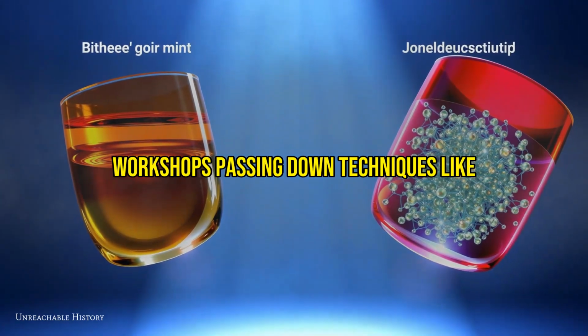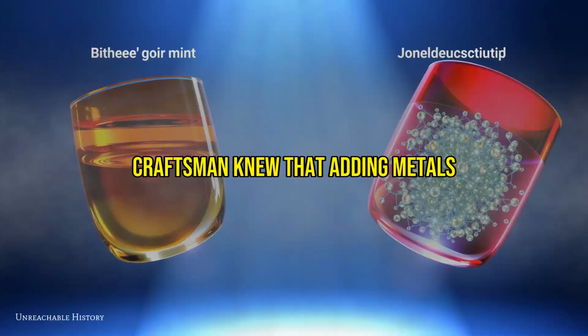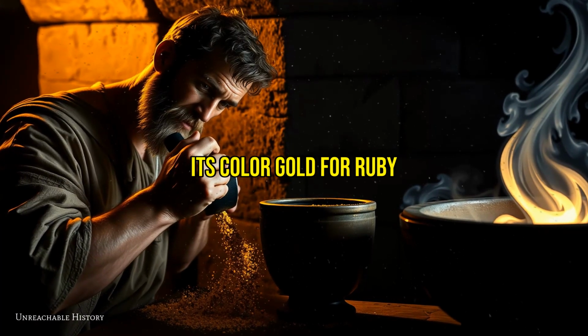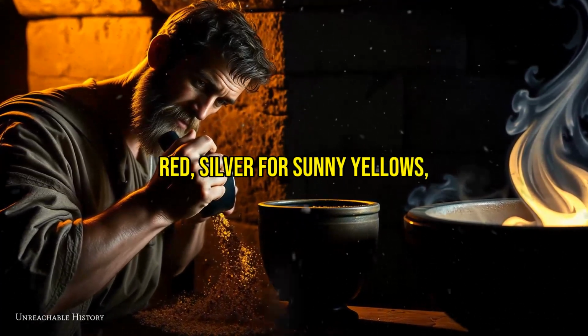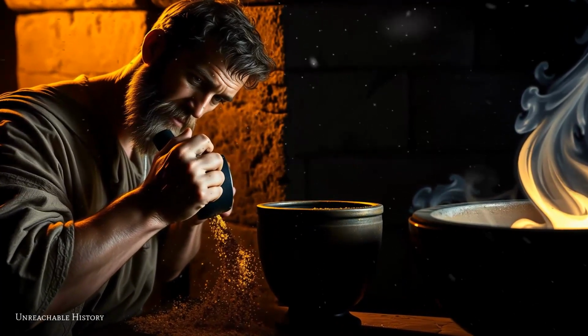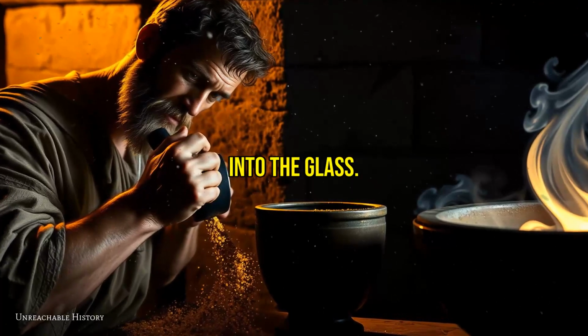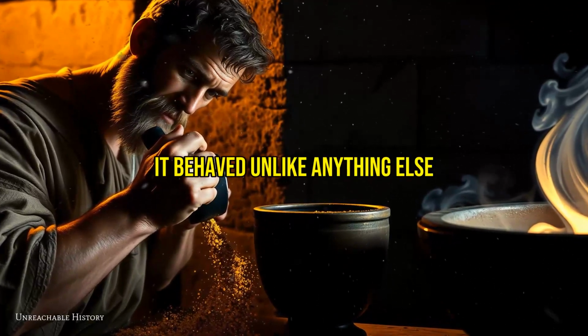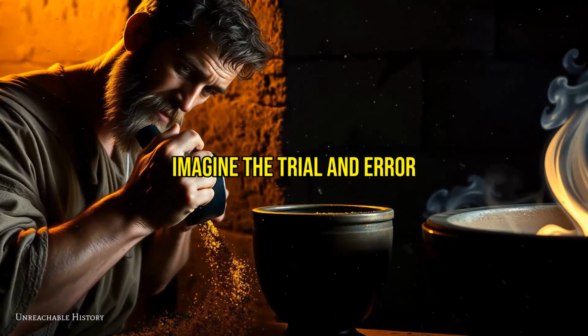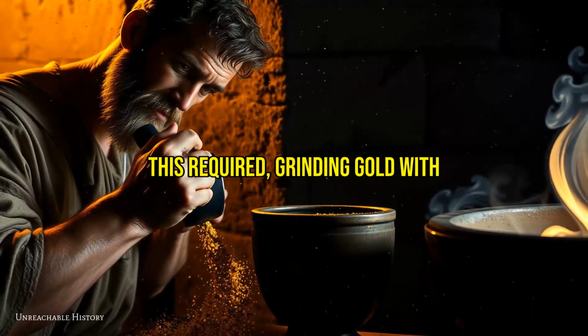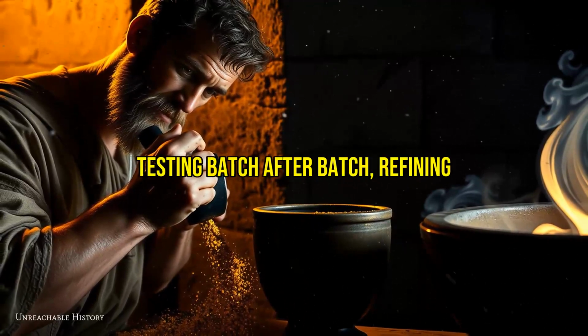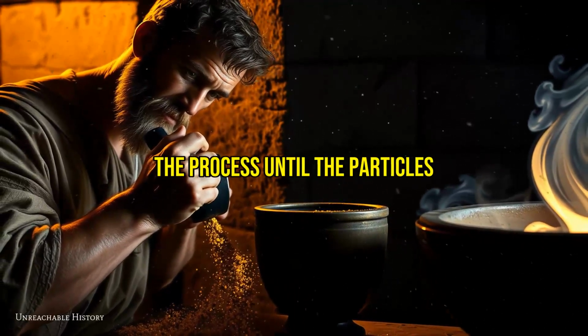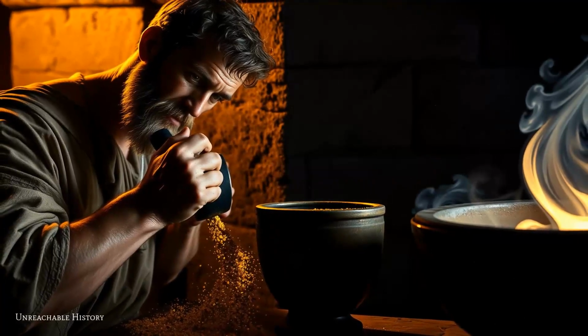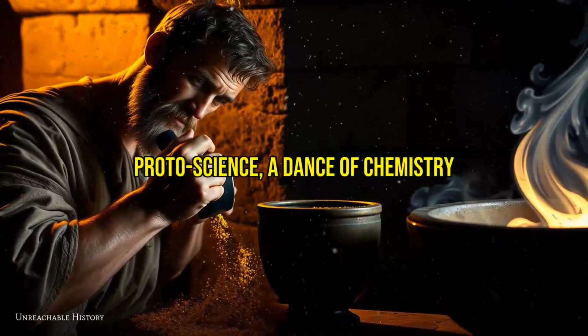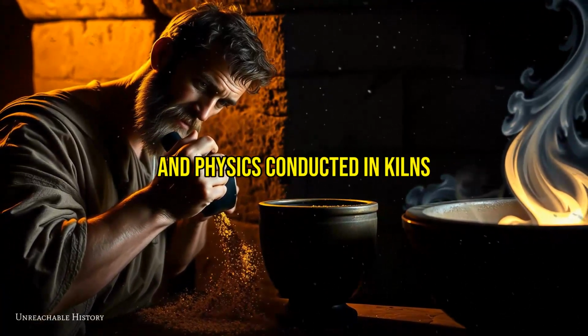Glassmaking in antiquity was a fiercely guarded trade, with workshops passing down techniques like sacred texts. Craftsmen knew that adding metals to molten glass could alter its color: gold for ruby red, silver for sunny yellows, but the Lycurgus Cup's creators went further. They didn't just dissolve metals into the glass, they ground them into dust so fine it behaved unlike anything else in nature. Imagine the trial and error this required, grinding gold with mortar and pestle for hours, testing batch after batch, refining the process until the particles were small enough to scatter light predictably. This wasn't decoration, it was proto-science, a dance of chemistry and physics conducted in kilns rather than labs.